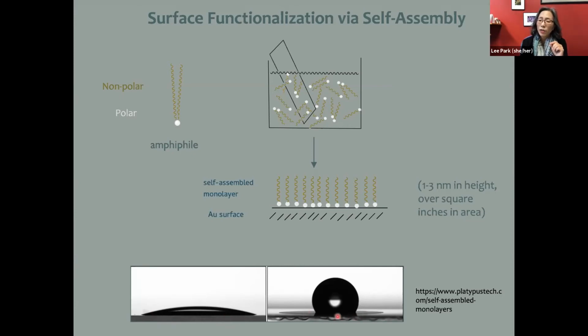But if you take a surface that's hydrophobic, as this surface would be with all these greasy tails sticking up, then the water drop, when it interacts with this surface, is not interested in interacting with that surface. So the water will tend to bead up so that the water molecules can interact with each other as much as possible and minimize the interactions with the surface. So you dip your slide in this liquid. You can't tell that you've done anything by eye, but you can tell by doing this simple test, and you can see that you've changed the surface chemistry.